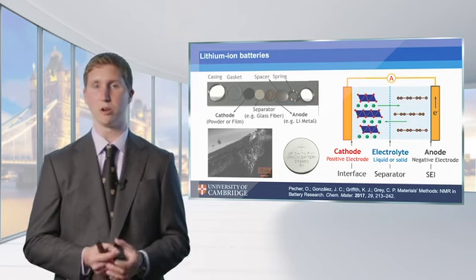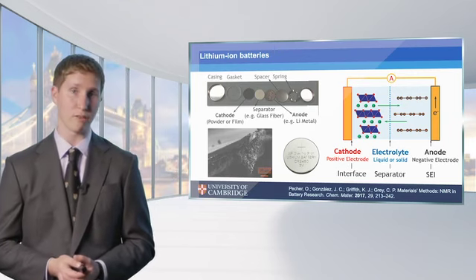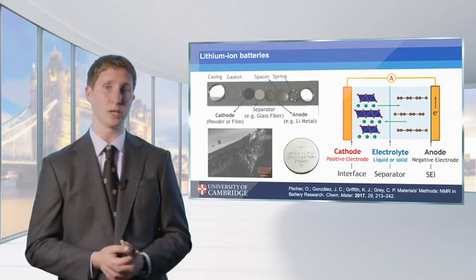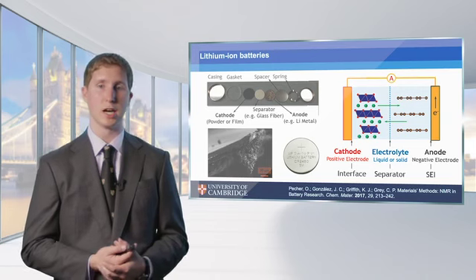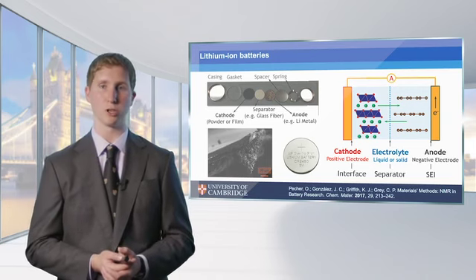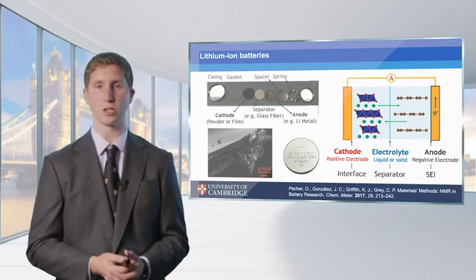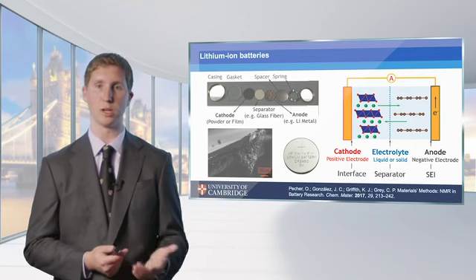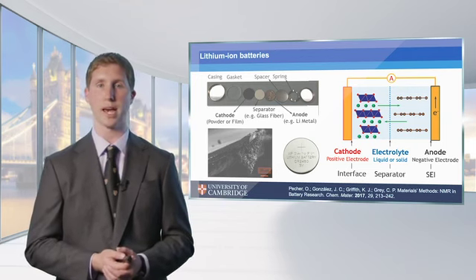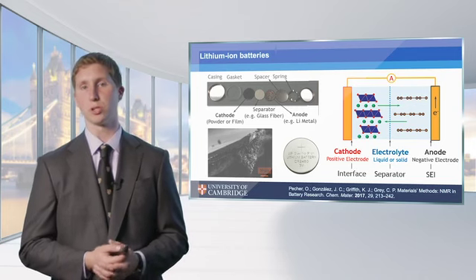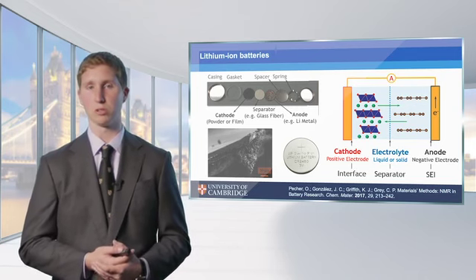And our anode in almost every lithium-ion battery now is graphite. Graphite is good because it offers high energy density, and it operates at a very low voltage near lithium metal, which allows it to get the maximum cell voltage possible when paired with a cathode. But there are issues associated with that, and one of those issues is related to safety.